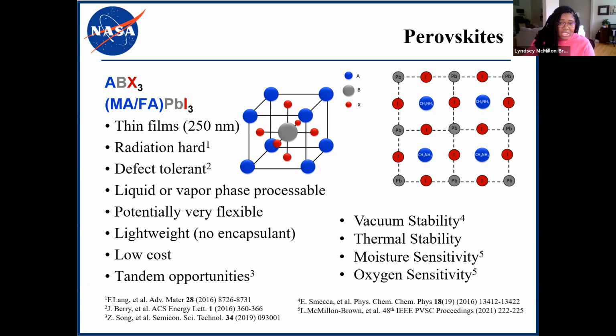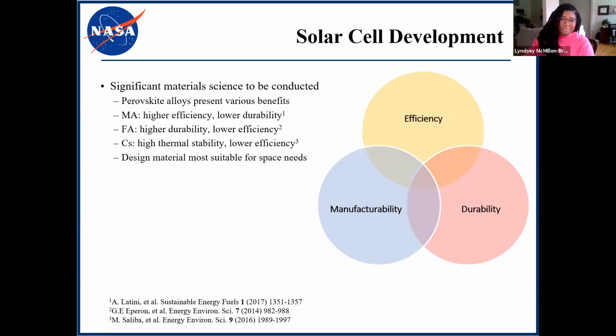Not all of the layers currently in a perovskite solar cell device are suitable to withstand the harsh environment of space. Specifically, these perovskites struggle a bit with vacuum and thermal instabilities, as well as moisture and oxygen sensitivities. The moisture and oxygen sensitivities, however, those concerns disappear when we put a device in space. So we do believe that all these challenges can be overcome with significant materials development.